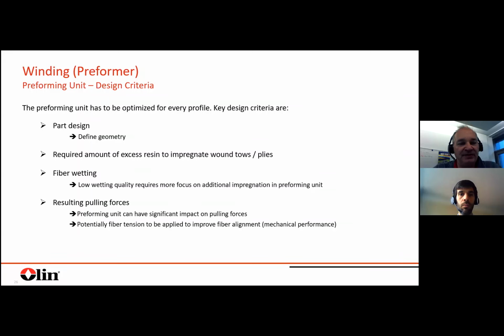And in this step also pulling forces are created. So you have to pull the fiber through something. If you have these deflection bars, you have additional forces. So that means that some forces are created, but this can also be not negative. To some extent, pulling forces are also good to improve the performance of your profile. So you have a better alignment. If you have later the winding step, you have a kind of higher resistance in terms of deformation of your fiber alignment. So by controlling the pulling forces and increasing them maybe to some extent, you can also improve a little bit the performance of your final profile.